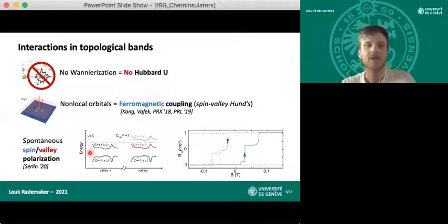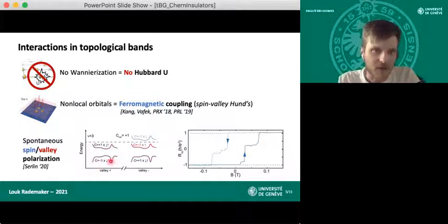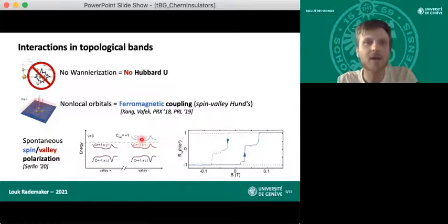So indeed, if you take TBG that you induced with a Chern number by breaking sublattice symmetry, you get a system that favors spontaneous spin-valley polarization. This was shown for TBG aligned with an hBN substrate to break sublattice symmetry. And there at filling 3, they propose you have this state where one valley is completely occupied, the other valley has one spin species not occupied, which means that the net Chern number of the occupied bands is +1. So this system is now a ferromagnetic insulator with a quantized edge current given by this Chern number of +1, which is known as a Chern insulator, or alternatively, the quantum anomalous Hall effect.